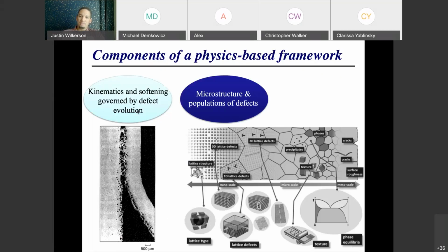Going along those same lines, it's important to account for the microstructure of the material as well as populations of defects. So you're going to hear in these physics-based models, quite often, obviously things like average grain size. It gives you an idea of the spacing between grain boundaries, but you're going to hear quantities like densities quite a bit. So dislocation density, that gives me an idea of the average spacing between dislocations, or how many dislocations there are in a unit volume of material.